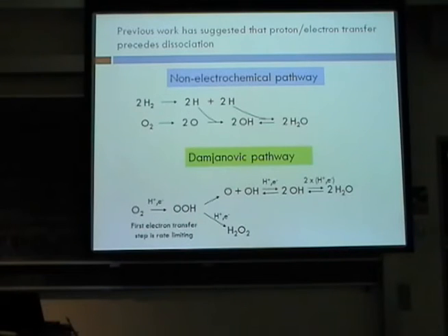And then the chemistry looks more similar to what you see up here, that you get sequential addition of protons and electrons. Right, and then in an undesirable reaction that we won't talk about much in here, you can also get hydrogen peroxide formation, which degrades the catalyst, and particularly the electrolyte connection to the catalyst, and is therefore a very undesirable product.